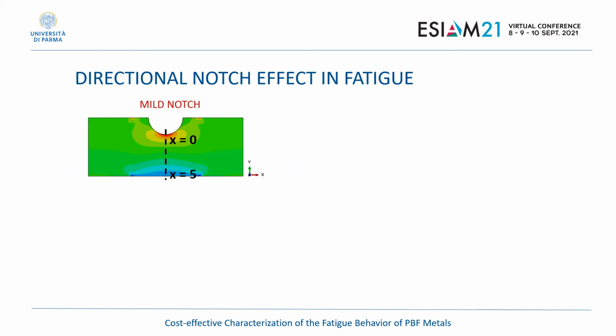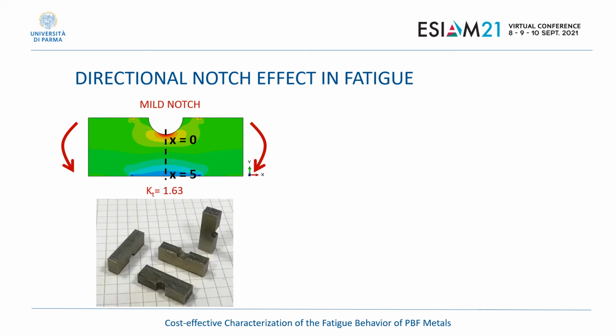We also investigated the notch effect in fatigue. What we did was essentially to apply a bending moment like this, as shown in this scheme. This loading condition generates a stress concentration factor of about 1.6, so we call it a mild effect. And once we have this characterization, we can develop and produce specimens with different orientations of the notches.